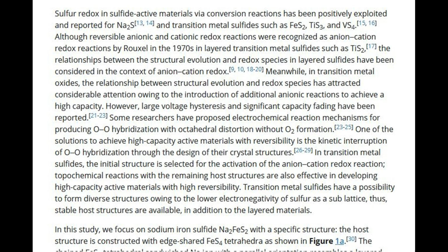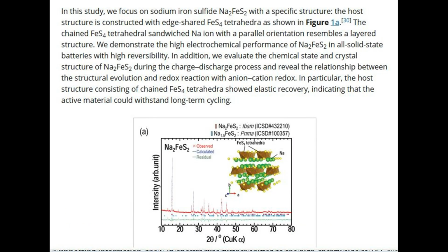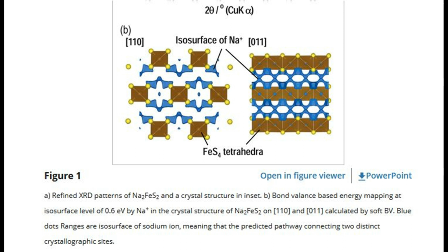In this study, we focus on sodium iron sulfide Na2FeS2 with a specific structure. The host structure is constructed with edge-shared FeS4 tetrahedra as shown in Figure 1a.30 The chained FeS4 tetrahedra sandwiching Na ions with a parallel orientation resemble a layered structure. We demonstrate the high electrochemical performance of Na2FeS2 in all-solid-state batteries with high reversibility. In addition, we evaluate the chemical state and crystal structure of Na2FeS2 during the charge-discharge process and reveal the relationship between the structural evolution and redox reaction with anion-cation redox. In particular, the host structure consisting of chained FeS4 tetrahedra showed elastic recovery, indicating that the active material could withstand long-term cycling.